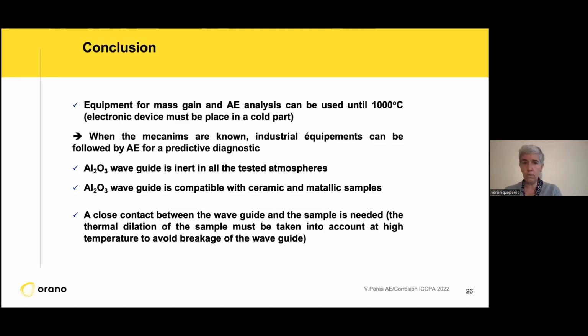And when we know the mechanisms involved in a corrosion system, as in zirconium or iron metal dusting, it will be possible to follow industrial equipment only with acoustic emission, which is a very nice tool for diagnostics. In this case, you need a waveguide which can transfer the elastic wave coming from the crack to the system, and we chose alumina, which is very inert in all the atmospheres we have here, and is also very compatible with all the mechanical samples we use, some ceramics.